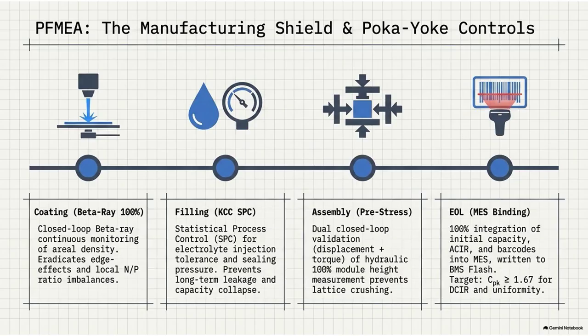Right, so if the coating machine stutters, even slightly, and lays down a patch of anode slurry that is a fraction of a micron too thin, that specific localized area on the foil will have an NP ratio that drops below 1.0. Exactly, which means in that microscopic localized zone, there are fewer intercalation sites than arriving lithium ions. It creates a localized lithium plating risk that the overall cell design cannot protect against. To prevent this, the PFMEA mandates 100% online continuous beta ray scanning.